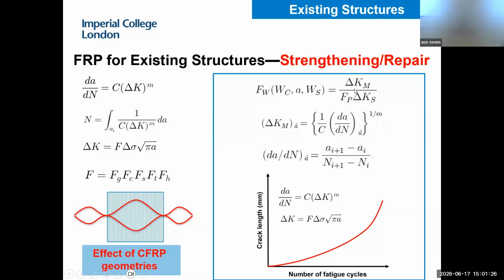Instead, we use the stress intensity factor from the testing curve. After the fatigue test, you have this crack propagation curve. Using this curve with the Paris law, you can calculate the stress intensity factor of your sample at any crack length—so you can calculate the real stress intensity factor.